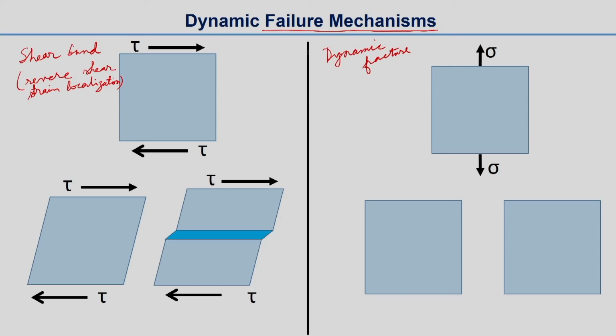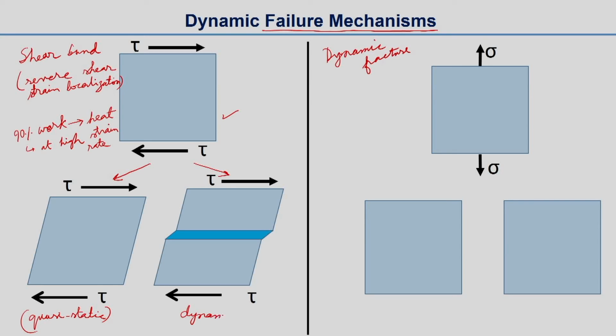Dynamic fracture. So, in the shear band at a high strain rate, most of the work, almost 90% of the work done in plastic deformation, is converted into heat. It happens at high strain rate. So, in these two cases, this is the initial configuration, and when you are shearing the material, there are two cases we are showing. The first one is slow loading, which is the quasi-static case, and the second one is dynamic, which is high speed loading. So, this is at high strain rate.